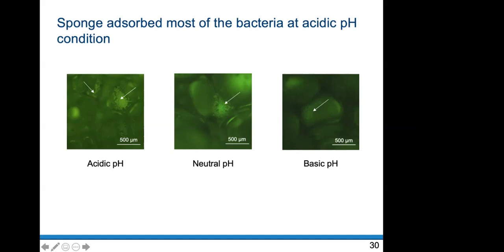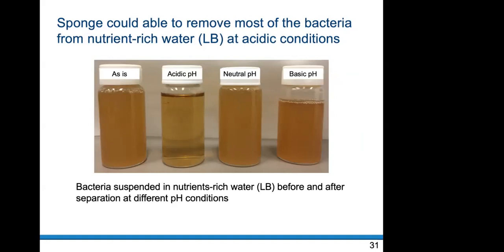But at neutral conditions, we see very few bacteria at the intersection of the pores. And at basic conditions, we see an even lower concentration of bacteria. This is obvious, because they are not completely attaching to the sponge surface at neutral and basic pH conditions. That's why we see a very low concentration of bacteria on the pore surfaces at neutral and basic pH conditions.